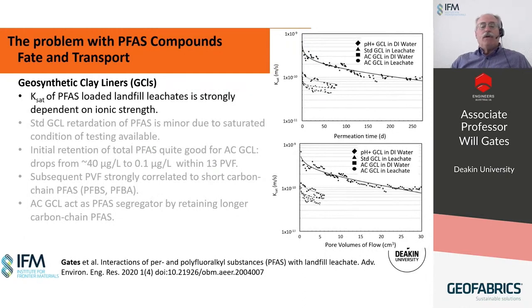Geosynthetic clay liners, though, are different. In a geosynthetic clay liner, you have smectite or montmorillonite as the main mineral component of the bentonite. We don't expect them to have a large impact on the absorption and retardation of PFAS transport, certainly not much more than what we see for compacted clay liners. And our recent experiments basically show this to be the case.